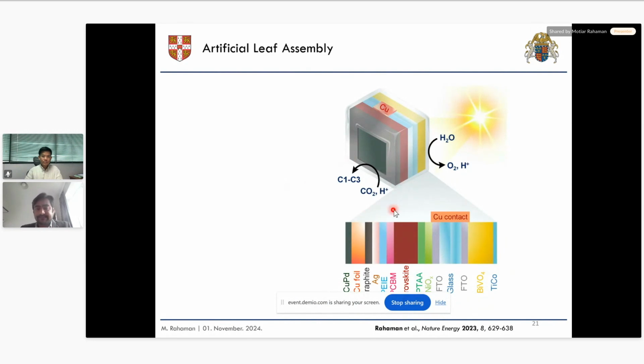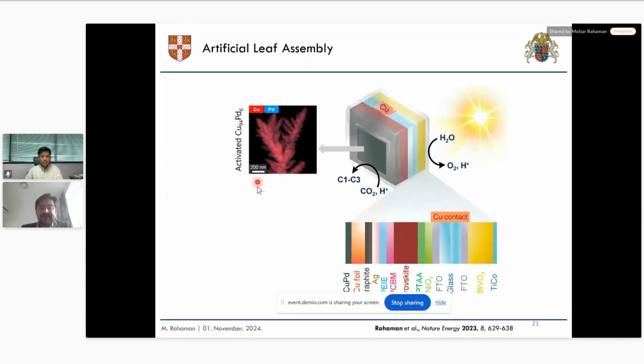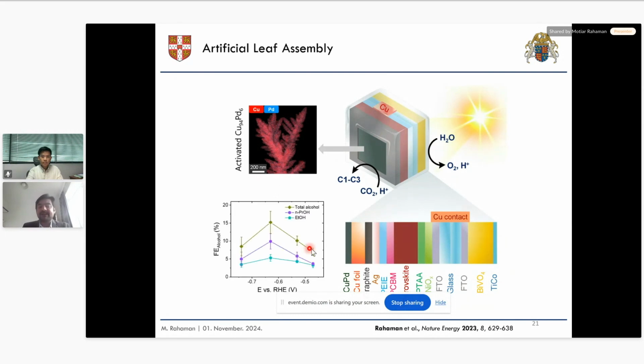Here comes the advancement. What type of catalyst can we use to get multi-carbon product from this standalone device? We developed a phase-segregated palladium copper catalyst. Palladium and copper form alloy quite easily. So we first make the as-prepared catalyst, and by thermal and electrochemical treatment, we separate the phase of copper and palladium. It is only 6% palladium with 94% copper,